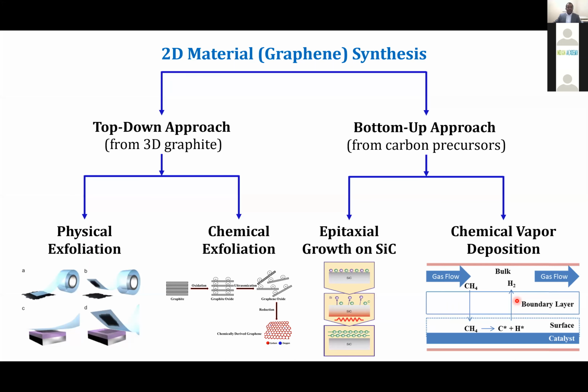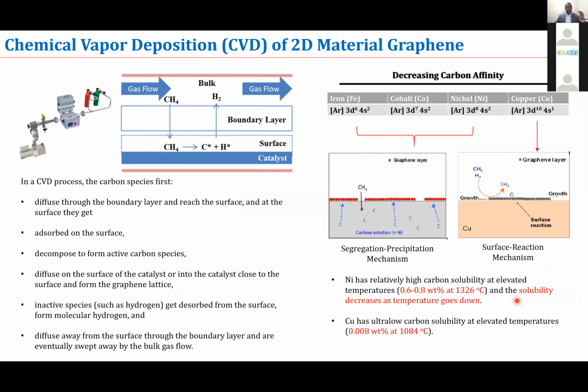As I discussed here, methane gas flows into the chamber, and the chamber is heated to a certain temperature. Depending on the temperature we set, the methane can dissociate, and there is a catalyst, because we need a catalyst, for example copper, nickel, cobalt, or iron, especially the transition metals, because that will lower the temperature for methane dissociation. Otherwise, we might need a very high temperature. So, for example, we use copper or nickel to dissociate methane, and then the carbon radicals can connect among themselves to form graphene.